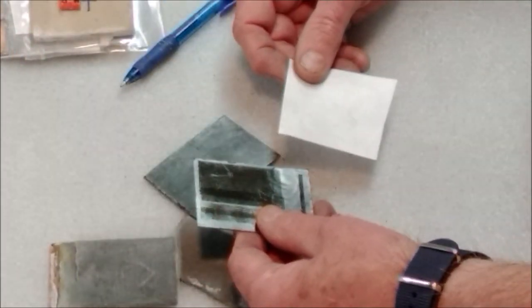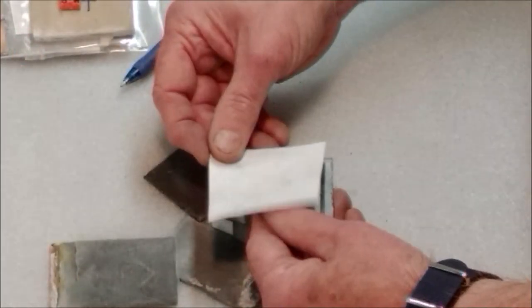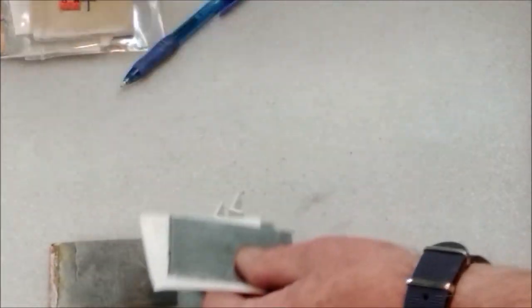The pattern that we used was a series of little circles, about six tenths of a millimeter in diameter, with about .25 millimeter spacing. As the laser scanned, every time it came across that circle pattern, it would turn on and then burn a little bit and stop. So we ended up with a series of dots. You could use any pattern, but you wanted to create this fuzzy open surface on the graphite.